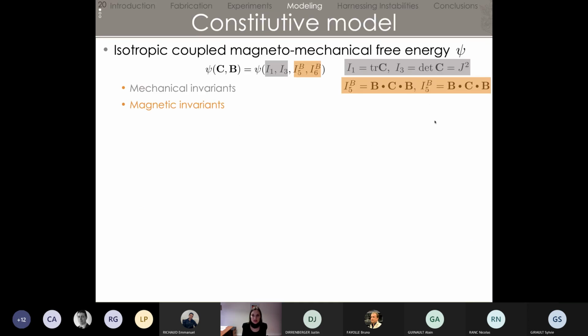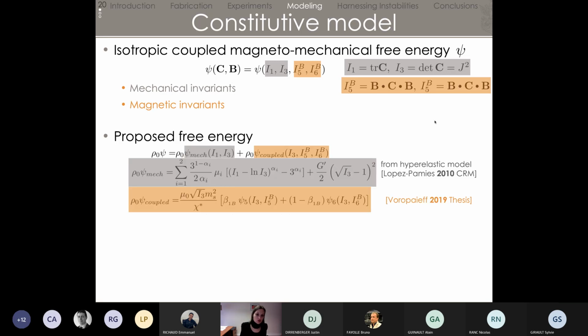So the idea, as I said, is not to model the particles because it's too complicated to compute their perturbation field, and we have hundreds of thousands of particles inside a sample. So the idea is to go phenomenological by proposing a free energy, isotropic because our samples are isotropic, and coupled. Inside that free energy, we have mechanical invariants, I1 and I3, as well as magnetic invariants I5 and I6. Sorry for the typo, I put I5 twice. And so the idea is to propose a free energy that describes the shape of our curves.